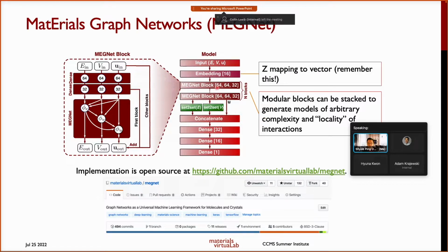Now, the other thing that we did was, instead of just using the atomic number as the input for our atoms, we map it to an embedding vector. This is a length 16 embedding vector for our atoms, and we use that as the starting point for our MEGNet model, right? After that, you have some concatenation followed by some deep neural networks, and what you have out there is an output layer that gives you your prediction, right?